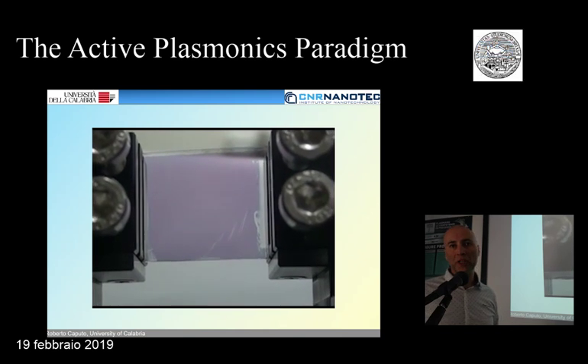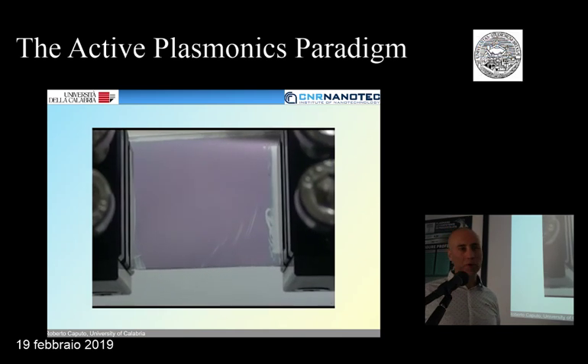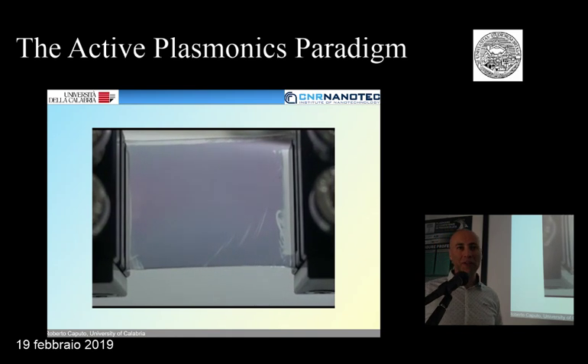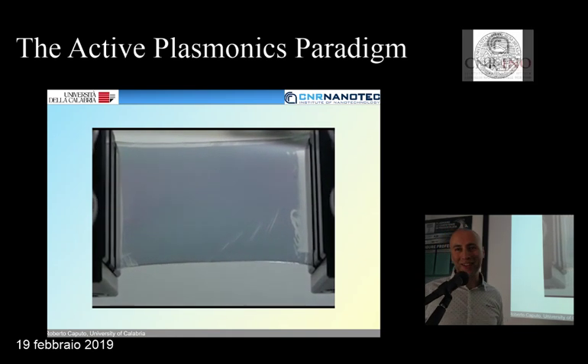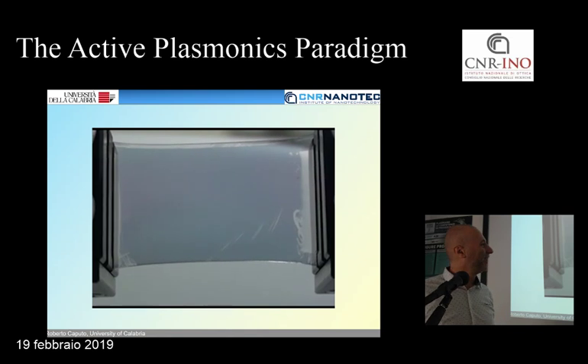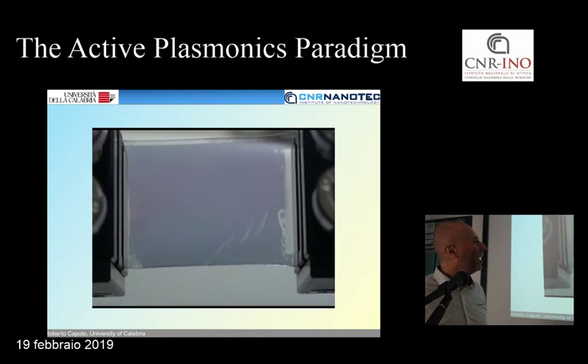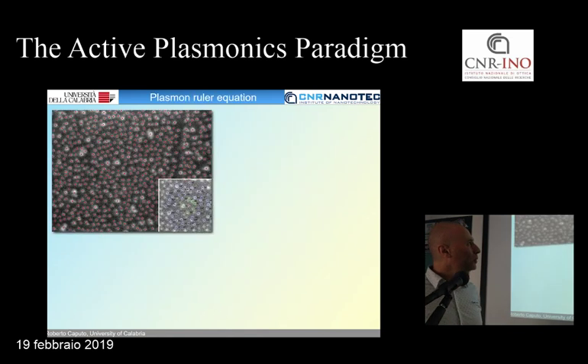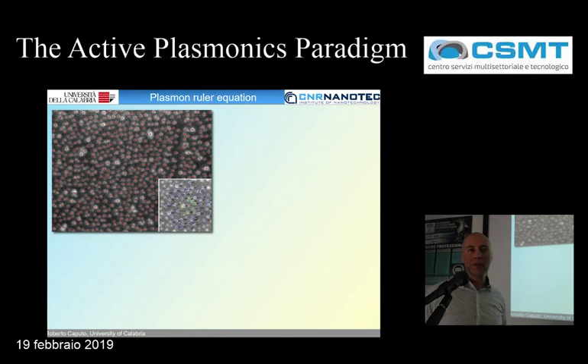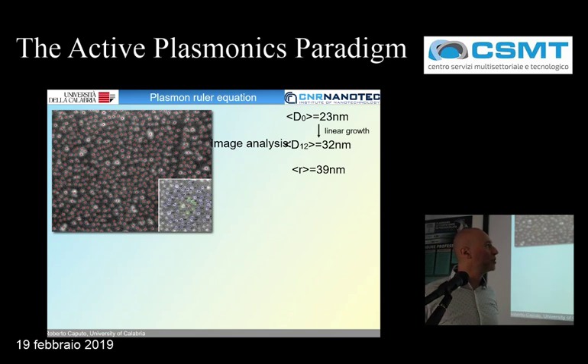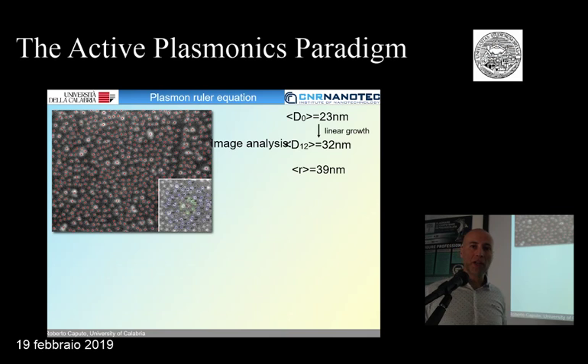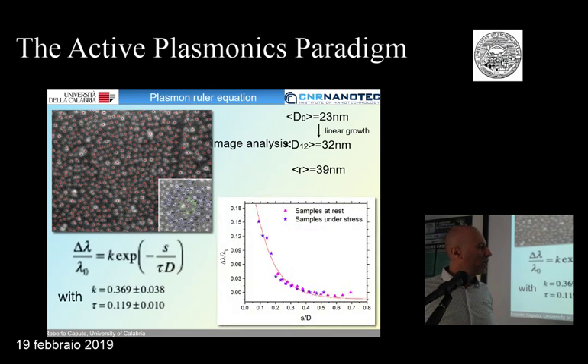So, you can stretch it many, many times without problems. Of course, if the substrate breaks from too much elongation, it doesn't work anymore. So we also tried to compare these results with the typical plasmon ruler equation, because we expect that when we are in a coupling regime, the change of resonance follows an exponential behavior. And we can show here that the sample at rest